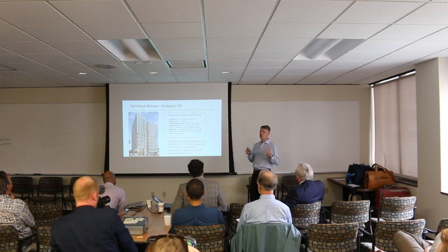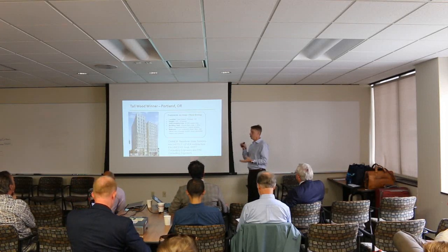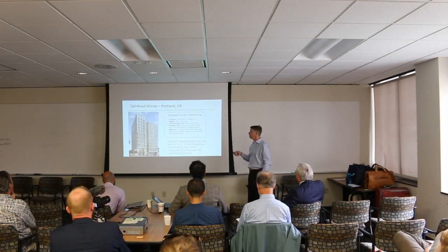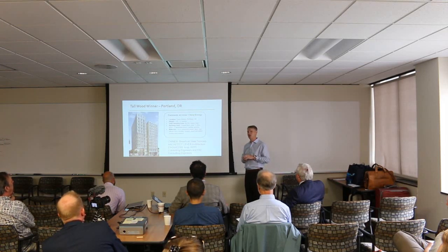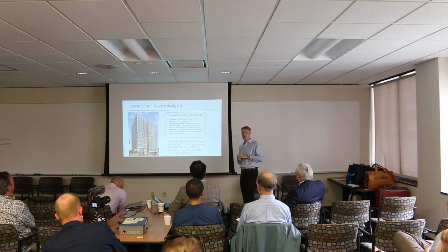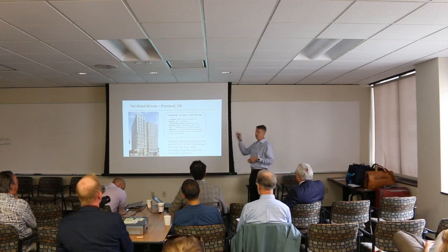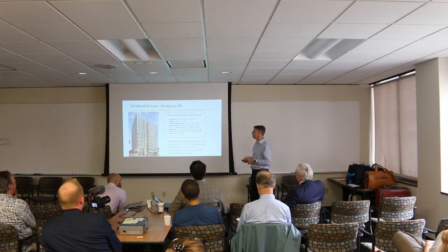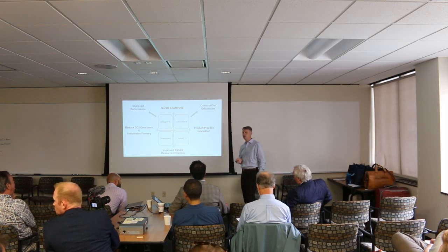But basically we've had to do some shear wall testing, some diaphragm testing, some beam to column connection testing. We've done floor ceiling fire testing at labs, proving that this concept works. If you're familiar with wood construction, it typically has a Class B, Class C flame spread rating. We actually did a floor ceiling assembly that has a Class A flame spread rating. That's the exact same that's required of steel and concrete. So now we've got a wood product that gets us a Class A flame spread rating. And all of a sudden it's like, why aren't we doing more taller mass timber buildings with CLT as the floor ceiling assembly? How big is it? It's a 5-ply. Yep.